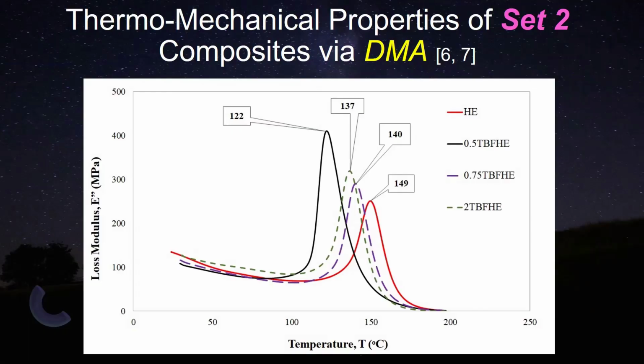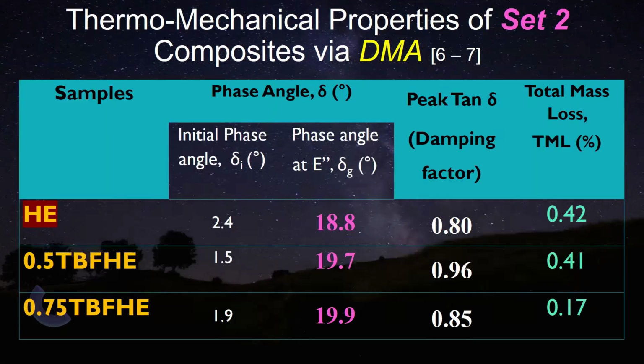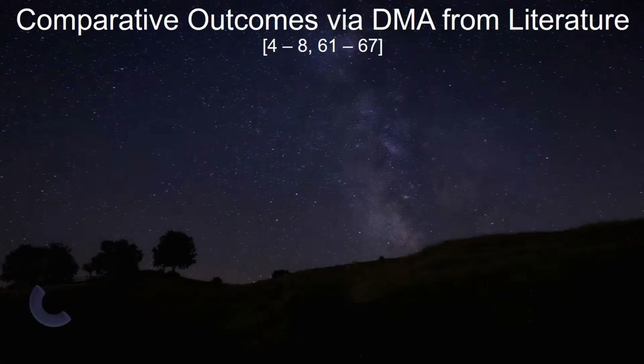Pretty interesting, but that was also insightful. When we looked at the damping factor or impact properties, we found that the high heat resistant sample got a damping factor of 0.8. However, with the treated sample, it actually enhanced. Although its Tg value decreased, the damping factor actually enhanced. So that's a good way we can still find it. We got the limitation, but we got a good sense of it.